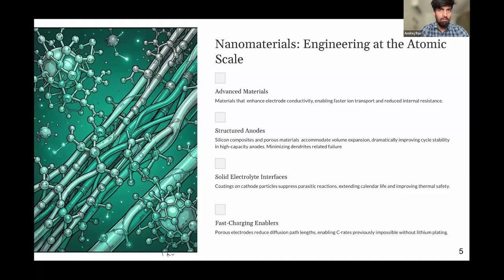So if we are aiming to go to that 500 watt hour per kg level, we have to shift to silicon based composites. But there are certain challenges in silicon too. What happens is, during this charge discharge process, silicon suffers from a high volume expansion and contraction, which leads to mechanical degradation and strength degradation. So we need certain materials which are porous in nature, which can act as a host to these silicon structures and minimize the risk of mechanical instability.